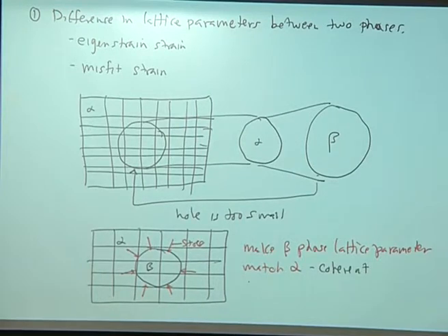In other words, on going through this cycle, after I put it back in, I haven't lost any lattice points. The lattice planes are still continuous. Okay, so that's important because it basically says you don't have any way of removing lattice sites on going from here to here. Your number of lattice sites is always conserved, so everything is coherent.